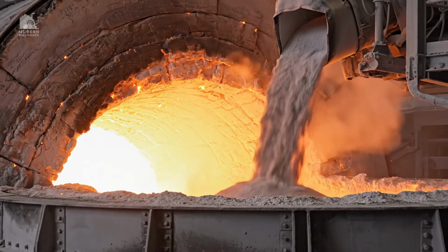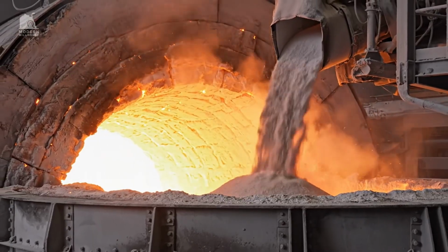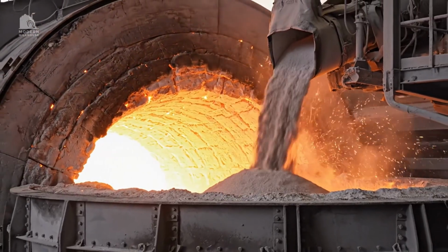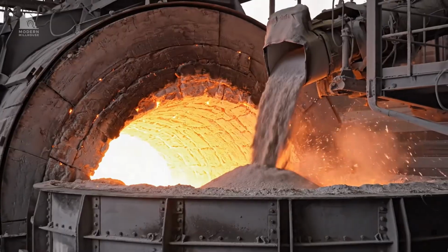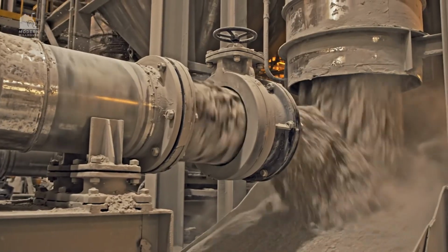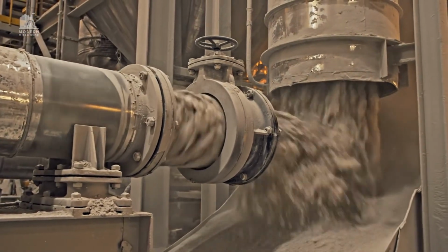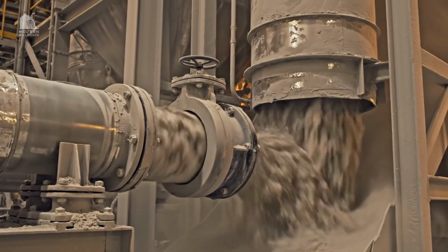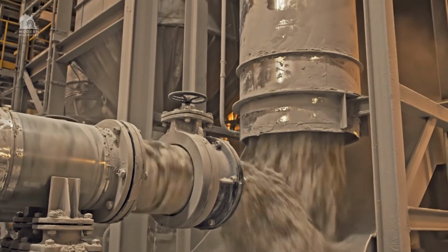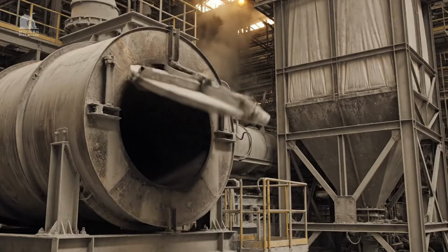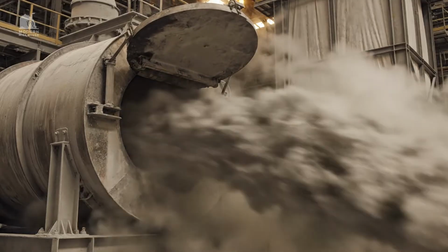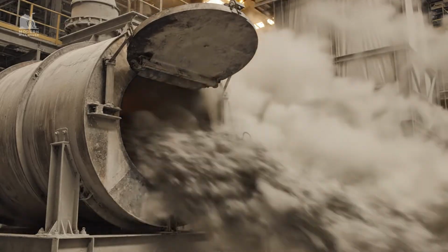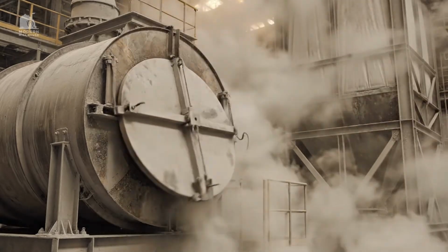By the time meal reaches the kiln inlet, much of the carbonate is already broken down, reducing kiln load. Dust cycles within the tower can affect chemistry, so bypasses and balancing keep salts and alkalis under control. Some plants use a bypass to remove volatile salts, protecting the kiln from buildup that can choke gas flow.